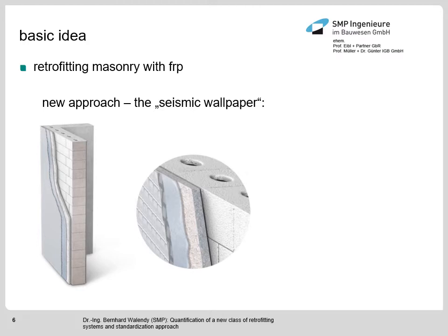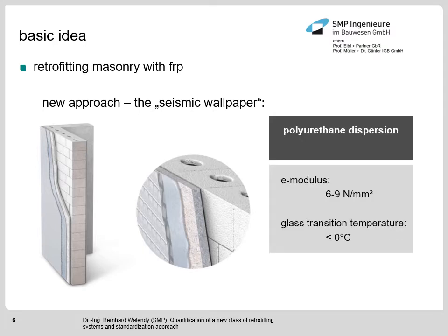The retrofitting system I want to introduce within this presentation, which has been developed at the Institute of Reinforced Concrete Structures, is called the seismic wallpaper. The seismic wallpaper differs strongly from commonly used fiber-reinforced polymer retrofitting systems, as it is applied directly on the plaster. And you don't use stripes, you apply the full surface. The main distinguishing feature of the seismic wallpaper are the mechanical properties of the glue, which is shown here. Polyurethane dispersion is used, and there is an elastic modulus of around 6 to 9 Newton per square millimeter. This is a very, very soft glue, and it behaves almost like an elastomer.